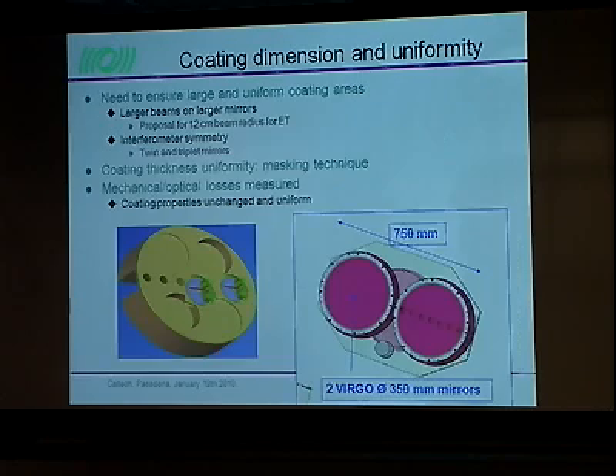One of the things that one should keep in mind is that people want this coating to be deposited on larger and larger surfaces. For example, you want the interferometer arms to be as symmetric as possible, so you want the mirrors placed in the two arms to be as symmetric as possible, and the only solution to do that is to coat them at the same time. But of course that means that you need to be able to deposit your coating in a uniform manner on a larger surface, and you need to check that when you start using this masking technique, which I use to make the coating as uniform as possible, you actually do not change the optical and mechanical properties of your coating.